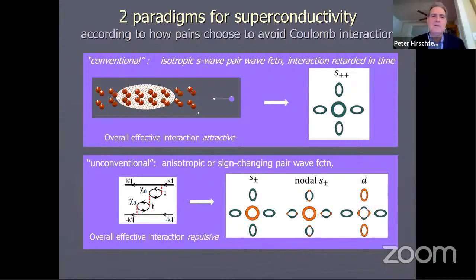So let me summarize a little bit. I have two classes of superconductors that I've told you about so far. One is the conventional superconductor paired by the electron-phonon interaction. It's overall an attractive interaction in the range of frequencies that take advantage of this separation of electron and phonon energy scales. And it gives you what we would call an S++ state, where the sign is the same everywhere, typically anyway. And then there are the unconventional superconductors, which typically give you anisotropic or sign-changing pair wave functions, which come from the exchange of electronic interactions. And I've drawn some diagrams here which are supposed to represent spin fluctuations, but it can be a number of different kinds of electronic excitations. And so you see that these always lead to sign-changing gaps. And in that case, the overall interaction is actually repulsive.